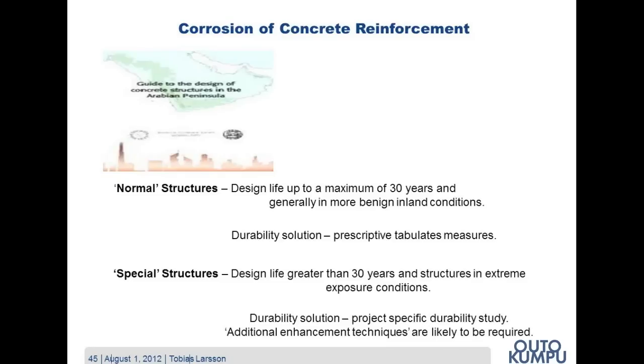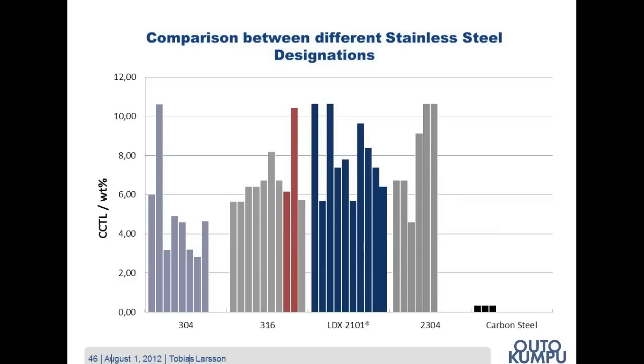We therefore promote the use of so-called predictive modeling, which is a way of assessing the level of chlorides in the concrete at depth and with time. So when you are using predictive modeling, you will have to know the steel grade's critical chloride threshold level, CCTL, which is the amount of chlorides that the steel can withstand without starting to corrode. We are using a so-called in-solution potentiostatic method. As you can see, just by choosing stainless steel, you will have a critical chloride threshold level about 10 times greater than that of carbon steel.